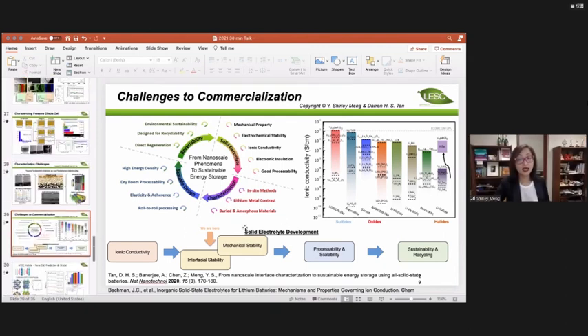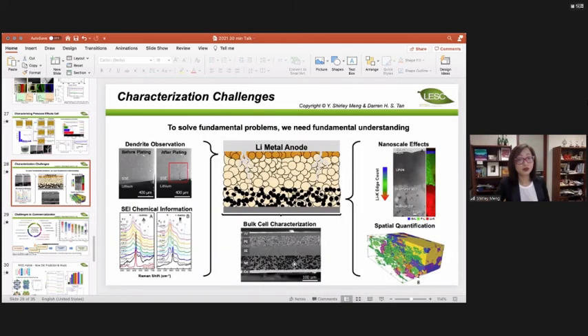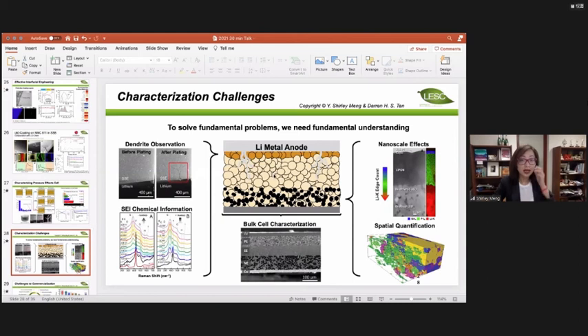Very good question. Today I didn't have too much time to talk about the challenge for the cathode electrolyte interface. Maybe I can use this picture to explain. If you look at this bulk cell characterization, this is a pristine material. The challenge is that even for intercalation cathodes, they experience 2 to 4% volume change. If the cathode shrinks or expands and detaches from the solid electrolyte, then you lose contact. Because it's solid state, the electrolyte cannot flow, and that will increase your cathode electrolyte interface impedance. To me, this is the single most critical problem for the cathode, and it is still not resolved.